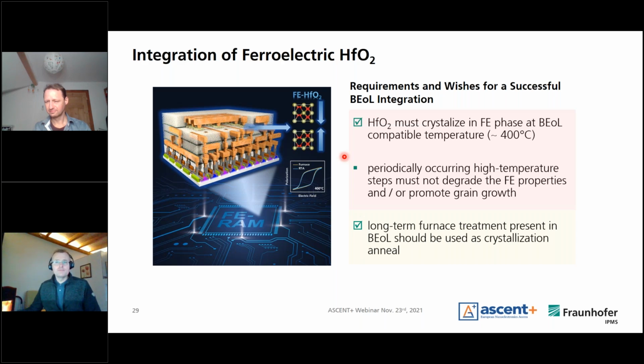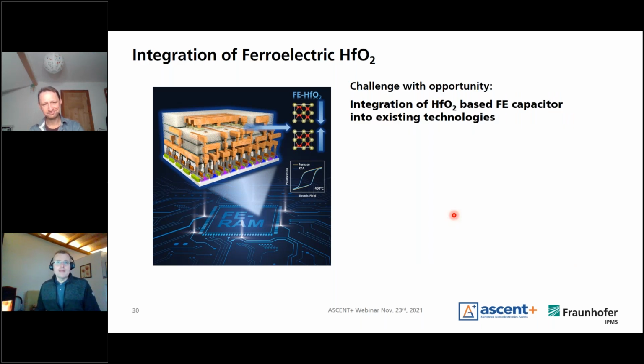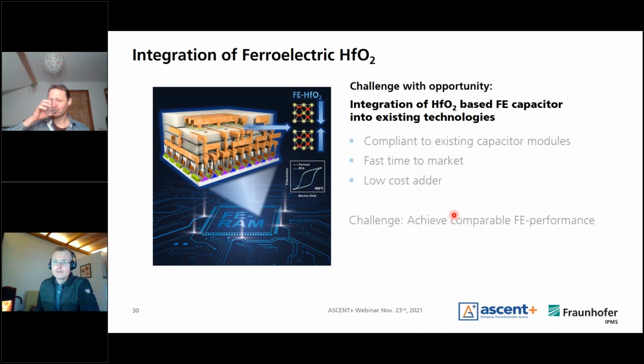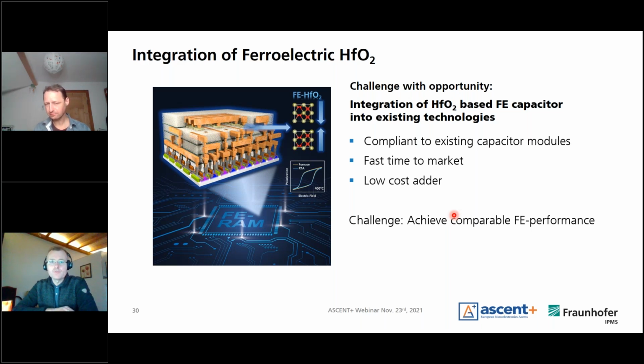That's just in brief some requirements for successful back-end of line integration of ferroelectric hafnium oxide. It must crystallize in the range of 400 degrees centigrade. That means the material must be doped in such a way that only a certain selection of dopants is possible to use in order to achieve exactly that. Also, temperature steps and subsequent processing shouldn't harm the material, as well as long-term furnace treatments. The challenge and opportunity given here is that we can integrate the ferroelectric hafnium oxide into existing technologies, also existing capacitor modules, which would allow fast time to market, but also a low cost adder. So you don't need to implement additional modules. You can maybe use and bend existing modules. The challenge is, of course, using existing materials and stacks, that we also achieve comparable FE performance.